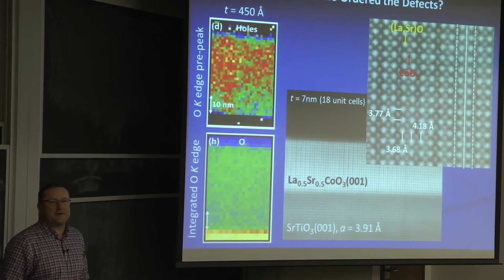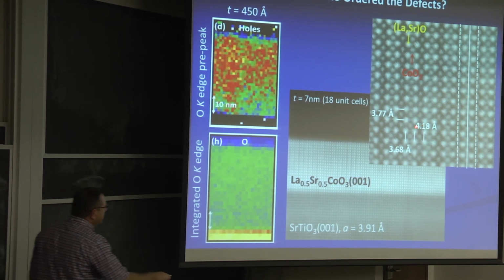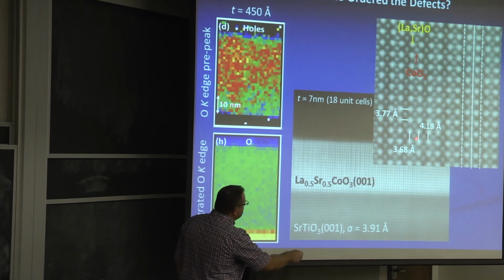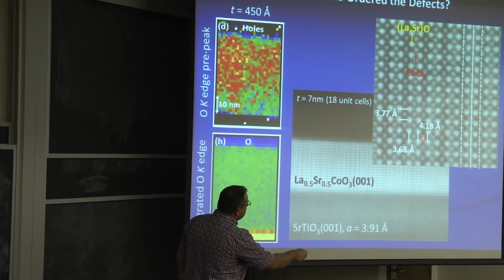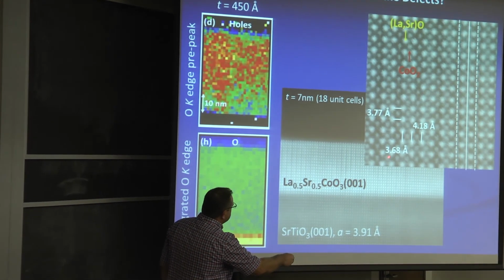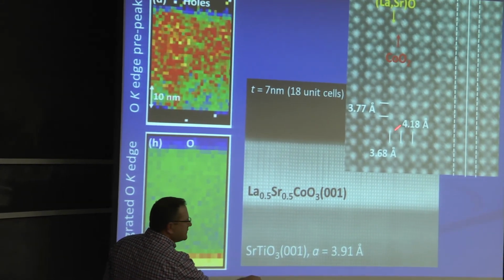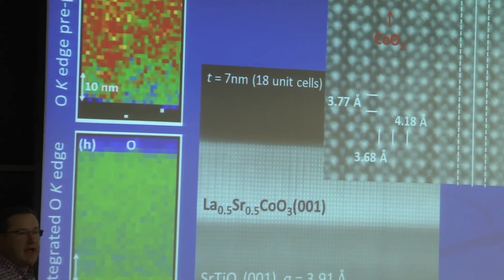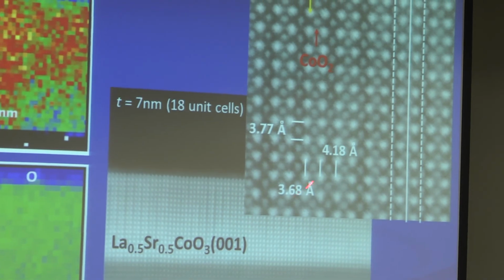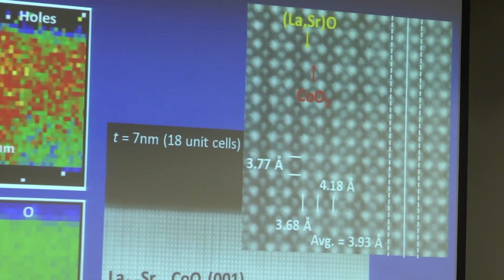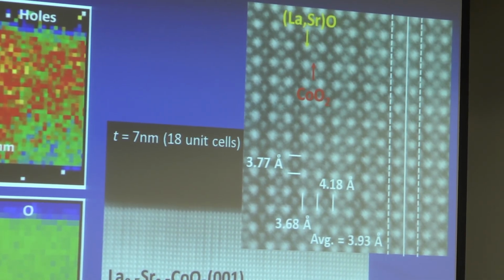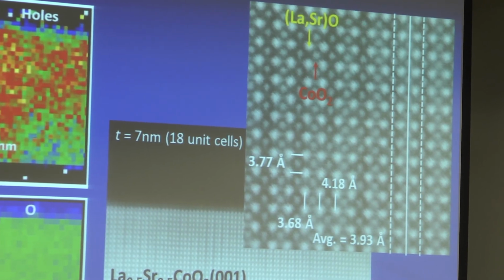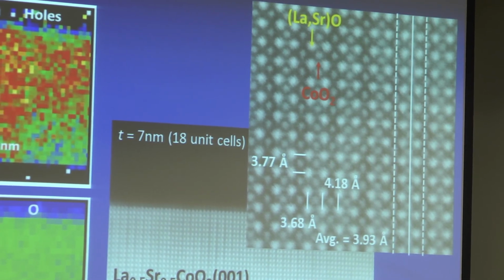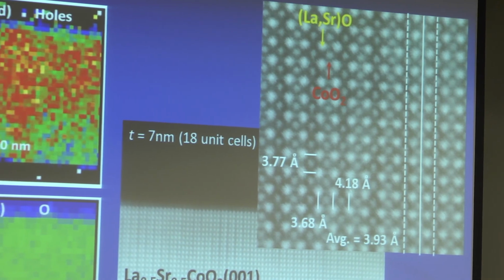I was actually looking around for something else. And of course, we knew if you take the oxygen out of one of the layers that its lattice parameter has to go up a little bit. The oxygen is the glue, and the one next to it has a little bit of a smaller lattice parameter. So we knew this thing was modulated, but I hadn't understood the significance until I took the average of these two numbers. The average of those two numbers is 3.93 angstroms, and the lattice parameter of the substrate is 3.91 angstrom. And it was like, wow, that's fantastic. I kind of get this now.